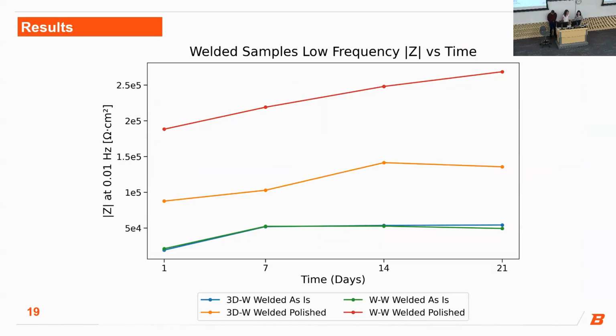For the welded samples, we observed significantly lower impedance than our single samples. This demonstrates that they are more susceptible to corrosion. There is still a slight increase in impedance over time, which means that the passive film is forming, but it's not stabilizing as effectively as our single samples. And again, the polished samples consistently had higher impedance than the as-is.